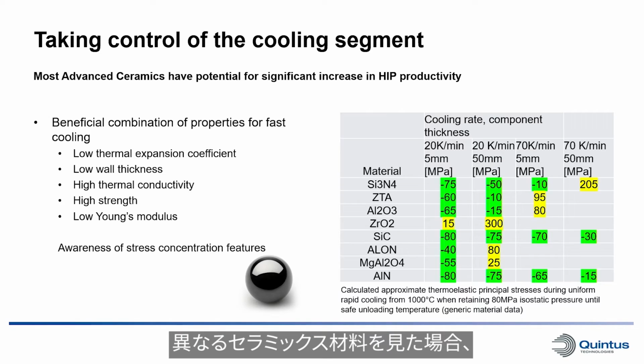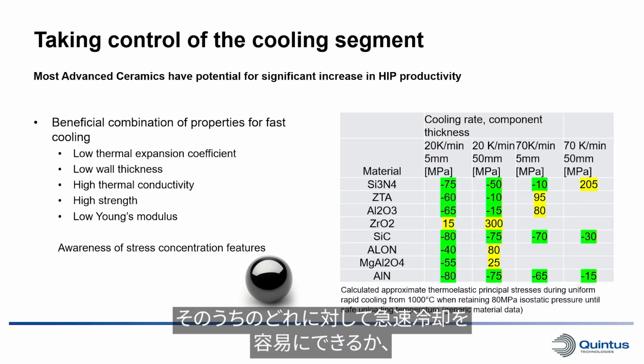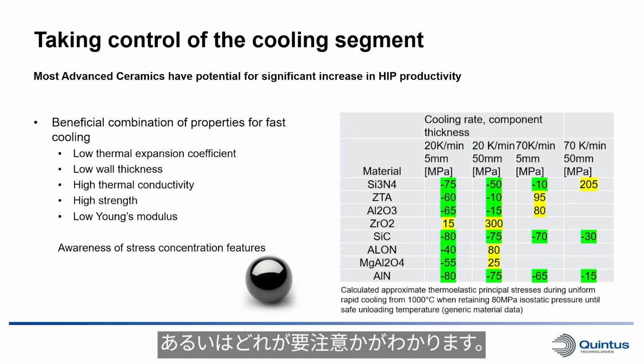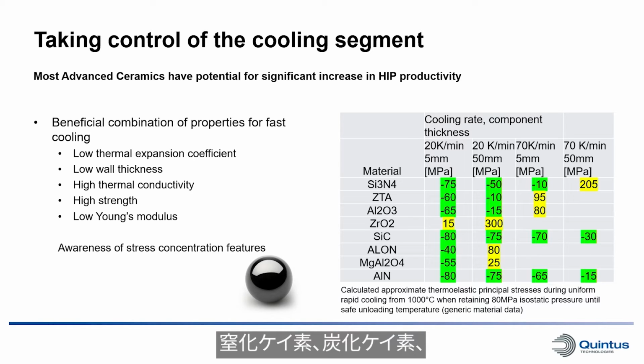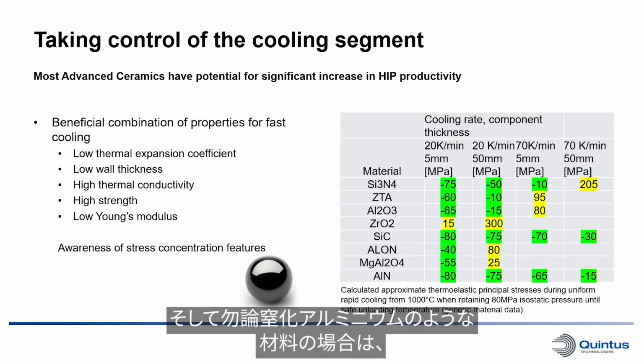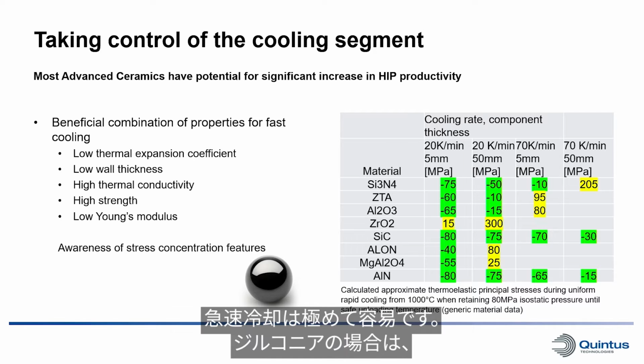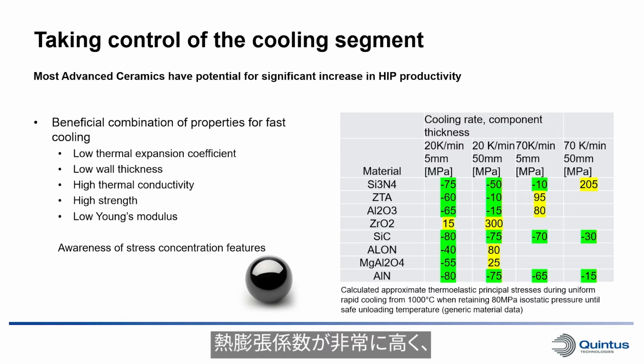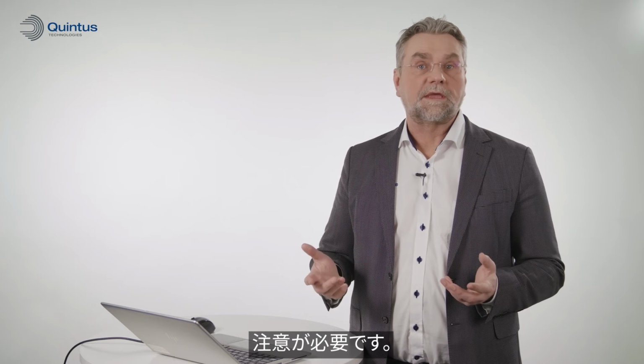So looking at different ceramic systems, we can see which ones we can say is simple to do rapid cooling with, and which ones we need to take more care with. Materials like silicon nitride, silicon carbide, and of course aluminum nitride will be very easy, while when it comes to zirconia, which has a very high thermal expansion coefficient and very low thermal conductivity, there we will of course need to take care.